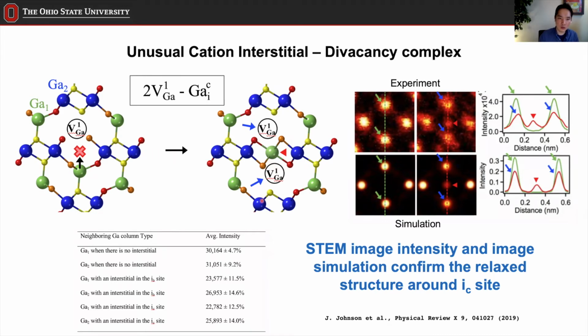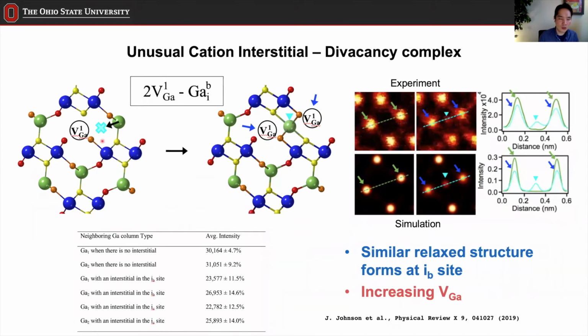But then we also see the same thing surrounding the IB site as well. So the same exact thing happens. It's the same mechanism and same intensity going up and down, but it is happening surrounding the IB site. So the complex formation happens both surrounding the IC and IB site. We were able to see both of them. All right, so that was a pretty exciting discovery, because we were able to confirm the very unusual structure that was predicted earlier, and that was done by this direct observation.